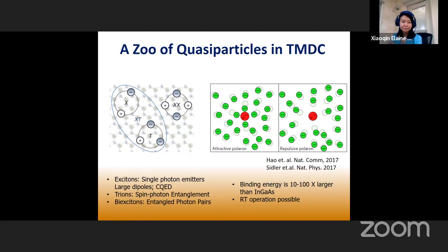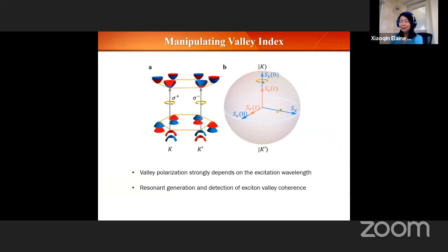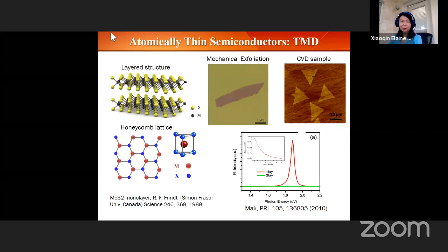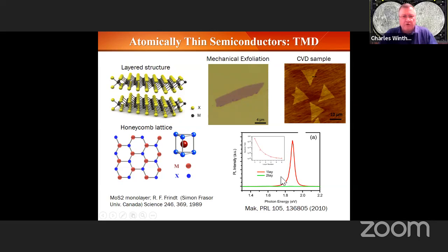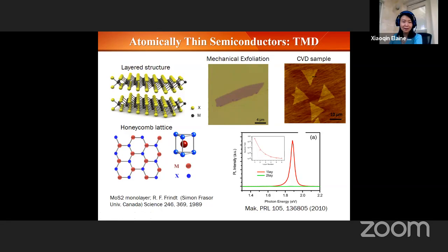I see. And what's the experimental signature of a trion versus an exciton? So I don't have a perfect plot, but if you just take these simple optical spectra, either in photoluminescence or absorption, you see an additional peak at low temperature popping up at the low energy side of the exciton. I see. So it looks like a satellite to the normal excitonic emission. Correct. At a lower energy. And to confirm it's a trion, you can apply an electrical field or start adding additional charge into the semiconductor. Then you can see their weight goes up or down.